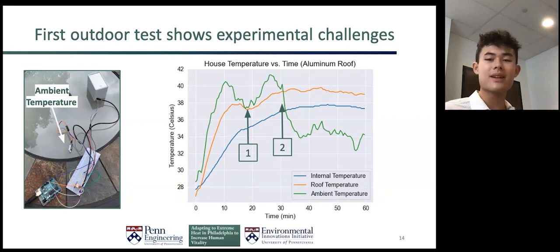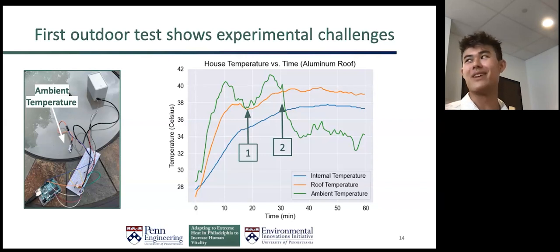And moving forward, we'll carefully monitor the weather so we can get results that can be compared day to day. And then the second arrow, which shows the ambient temperature dropping from 41 degrees Celsius to 34 degrees Celsius, was because I realized halfway through that there was a big problem with this setup. And it's depicted on the left. The ambient temperature sensor is sitting on the table, and it's actually measuring the temperature of the table, which was heating up from the sun. So by moving it off the table and suspending it in midair, I was able to get a better reading.